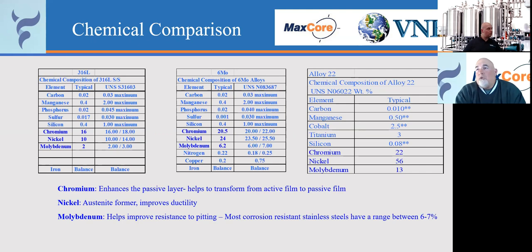Instead of 16 to 18, 20 to 22% chromium, nickel 23.5 to 25.5%, molybdenum 6 to 7%. And then you get into your higher alloys like alloy 22, you jump up to 22% chromium, 56% nickel, and 13% molybdenum content. So keep in mind what these alloying elements do. That's where you get your corrosion resistance from in these three products. But you also have to keep in mind that as those numbers go up, so does the cost of the material.